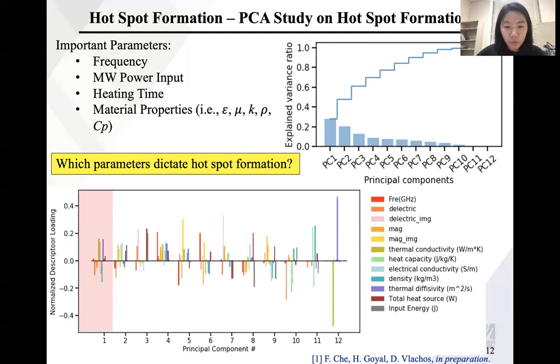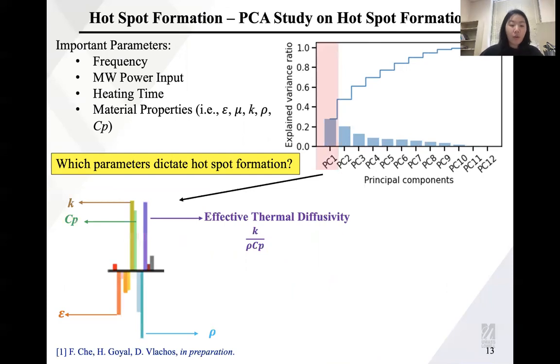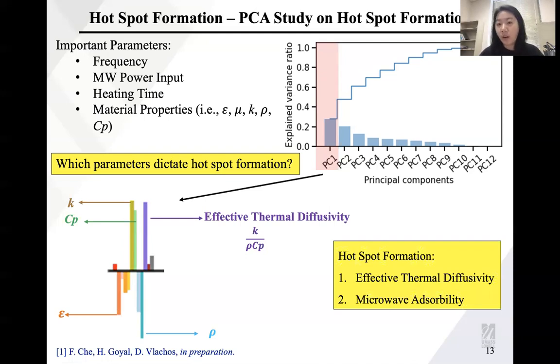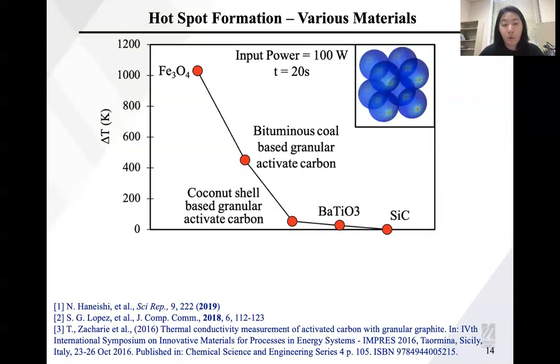So we further zoomed in on PC1. What is our PC1? Well, we found that the effective thermal diffusivity is the dominant factor, which is related to the heat capacity, the thermal conductivity, and the density of the material. And we also found another important factor, which is the dielectric constant of the iron oxide. So our current conclusion regarding hotspot formation is that effective thermal diffusivity will be one of the dominant factors leading to hotspot formation, as well as the particle needing to have microwave absorbability.